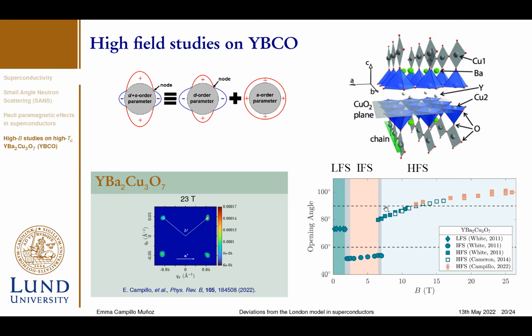As we see in the picture, the opening angle between the two Bragg reflections keeps increasing until it reaches a square structure. And once arriving at 25 Tesla, we see a plateau, and it's actually stabilizing at 100 degrees. What we think is that this is not driven by the London penetration depth anisotropies, but rather by the movement of the nodes when we apply a certain field.